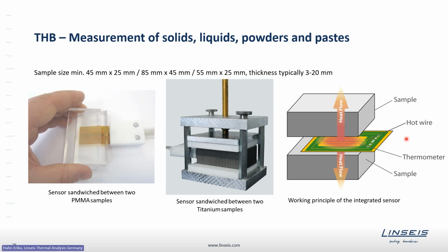Here you can already see the very basic measuring principle of this sensor. As mentioned, it's based on the hot wire technique where we have these wires acting as a Joule heat source, but at the same time also recording the temperature rise over time. This temperature rise with time will give indication about the thermal conductivity of the surrounding material. That is why the sensor needs to be embedded within 2 sample pieces so that the sensor is completely covered by the material to test.